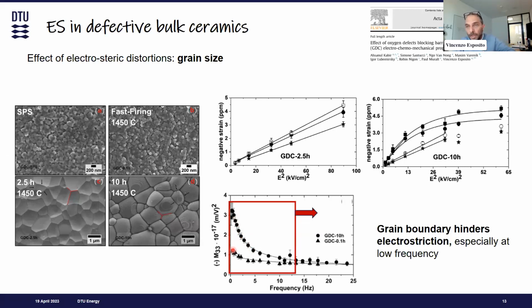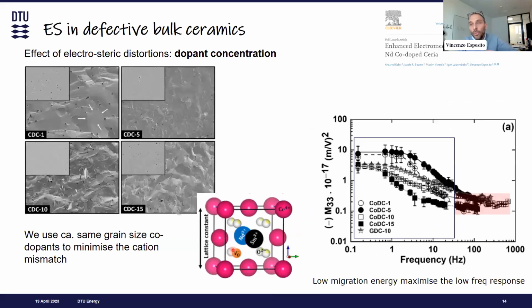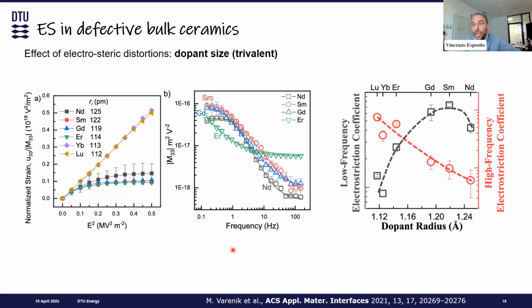So the first thing is that depending on the configuration of the vacancy, we actually can modulate the electromechanical response. So we were trying to understand this effect, not only in terms of grain boundary, but also more in general in terms of electro-steric distortion of the lattice, for example, using different dopants. And the starting point was to use a dopant or a combination of dopants that do not lead to any distortion to the lattice. And we have noticed that this configuration is the best in terms of electromechanical response, especially at low frequencies. On the other hand, when we start changing the size and the valence of these dopants, we change also the electromechanical response at different frequencies.